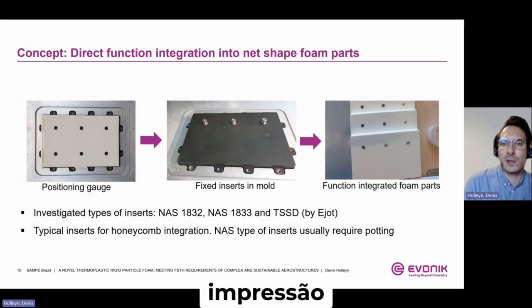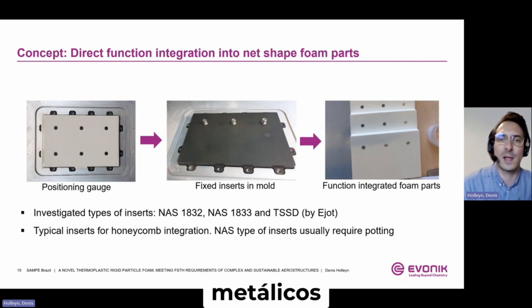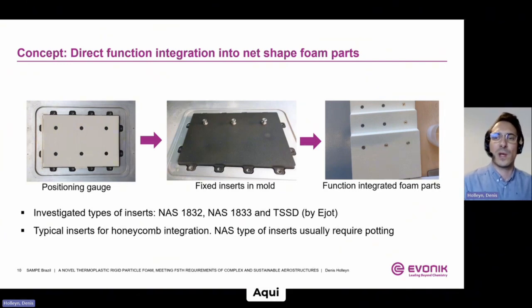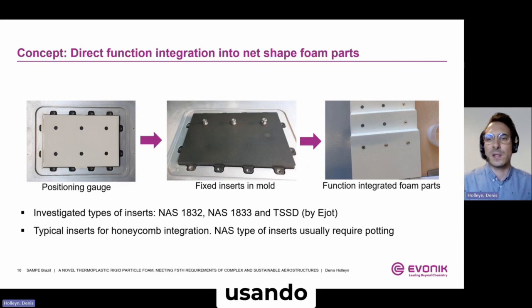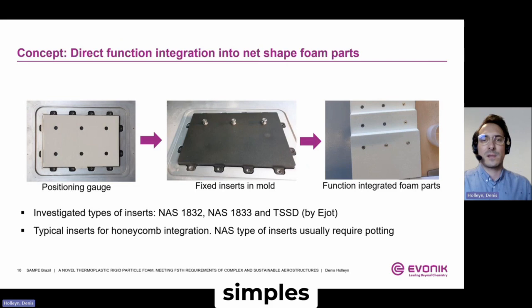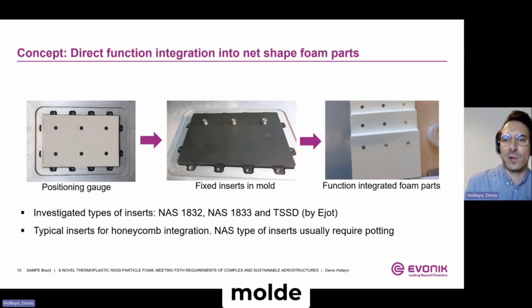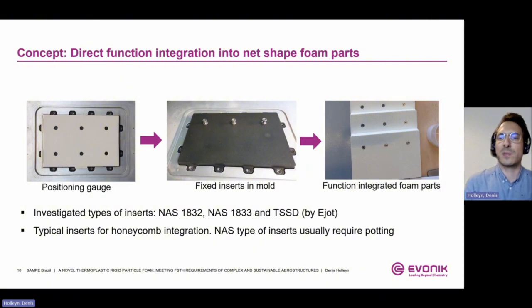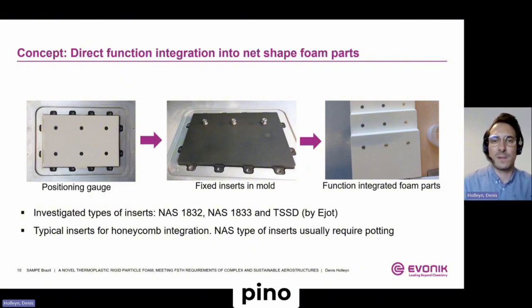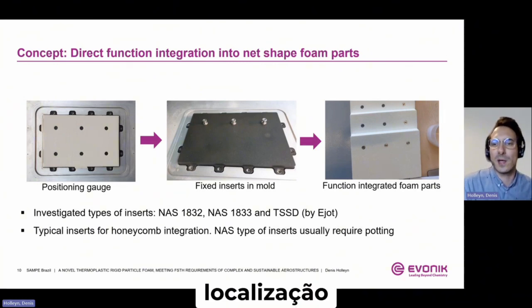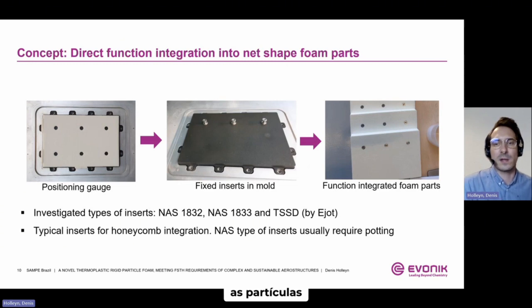And this slide gives you an impression of how insert integration of standard metallic inserts could look. In this case, we have integrated a couple of NAS type metallic inserts into a foam sheet by using a simple positioning gauge. These metallic inserts have been fixed inside of the mold by simple double-sided tape for demonstration purposes only. In real serial production, these metallic inserts would be put on a kind of pin inside of the mold in order to determine the location of the insert and to let the foam particles flow around the insert freely. The result is a foam sheet which includes multiple inserts in one production step and without any rework.